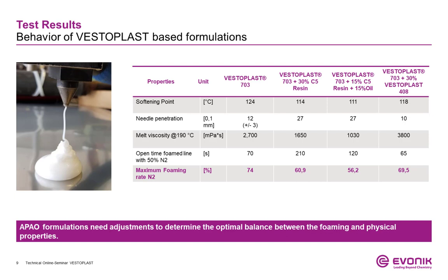It could be observed that the impact of oil on the foaming properties is quite significant. The oil itself has no cohesion or adhesion properties and is mainly used as a viscosity modifier. Therefore, the foamability of the formulation is reduced, a lower gas amount can be incorporated, and the bubble size is bigger. Resins are very crystalline molecules and increase adhesion, but there is a lack of flexibility due to their low molecular weight, which limits the capability of gas absorption.